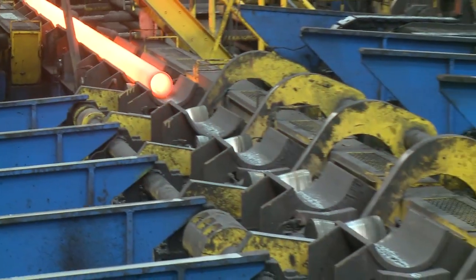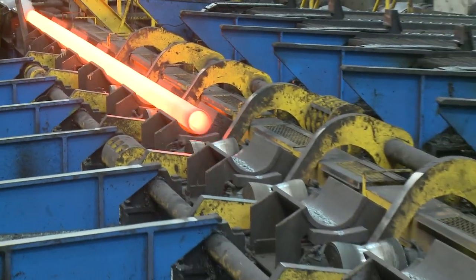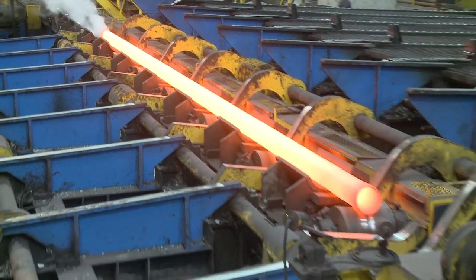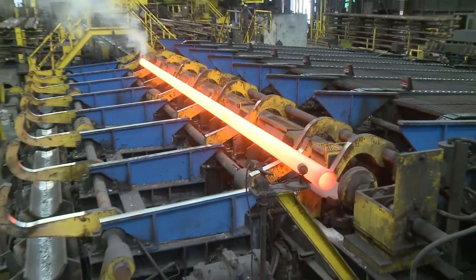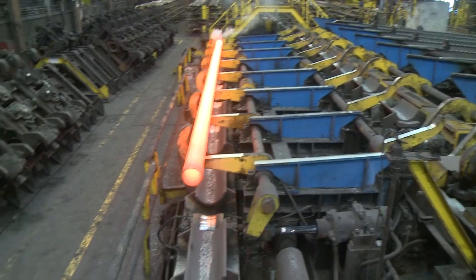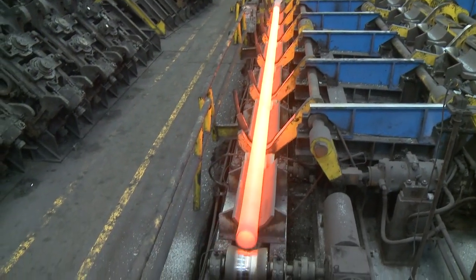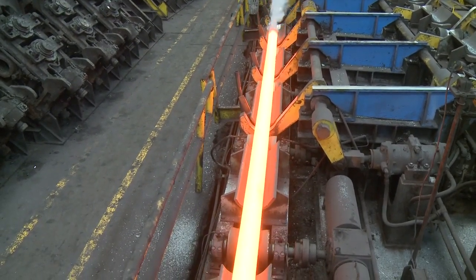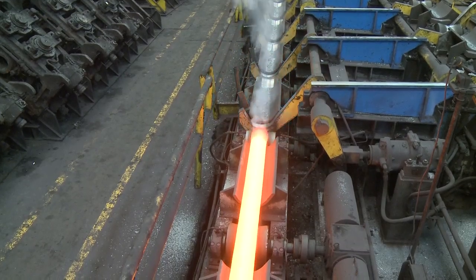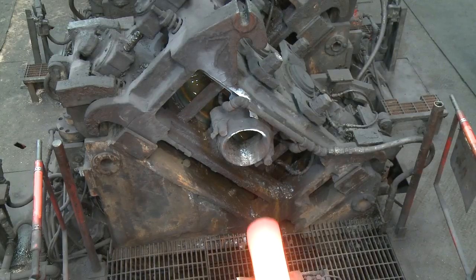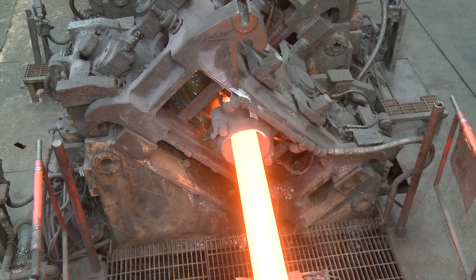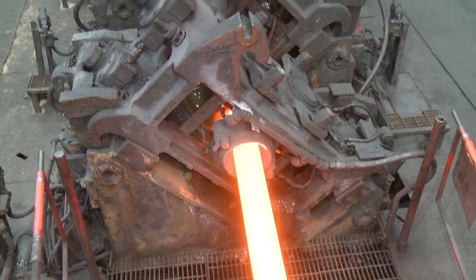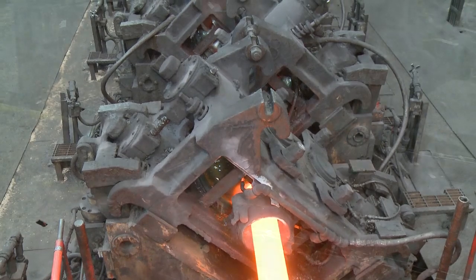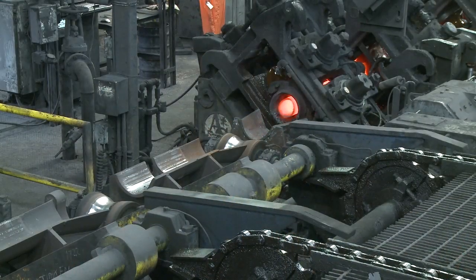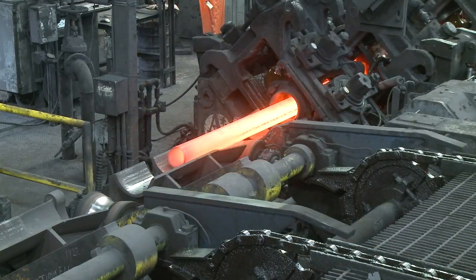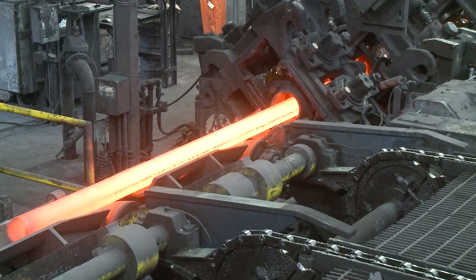In the next stage of our operation, we work to get a consistent outer diameter across the tube length by using a 10-stand reducing mill. Size ranges for this reducing mill range from 3.5 inches diameter up to 8.75 inches diameter. Like the versatility of our wall increments, the reducing mill can achieve any size within these dimensions, and we can produce orders in 1/1000th of an inch increments. We use different stands or reducing mill sets and adjust them according to the size requirements.